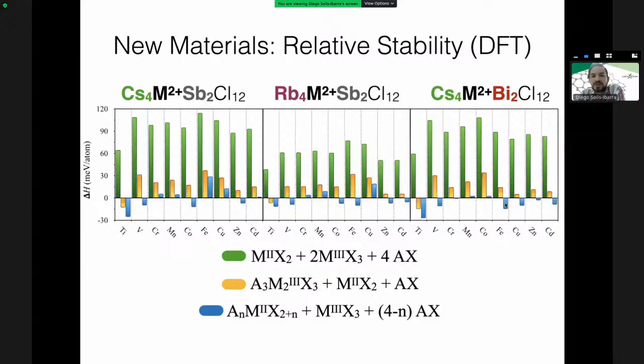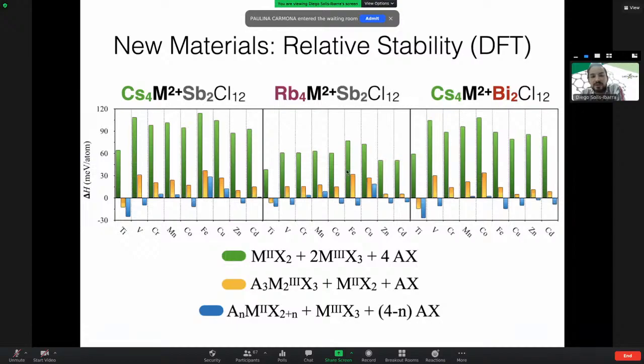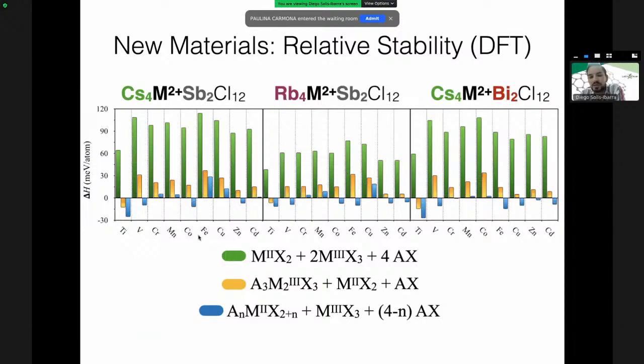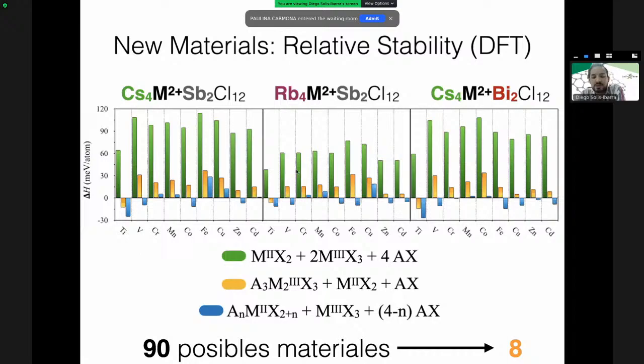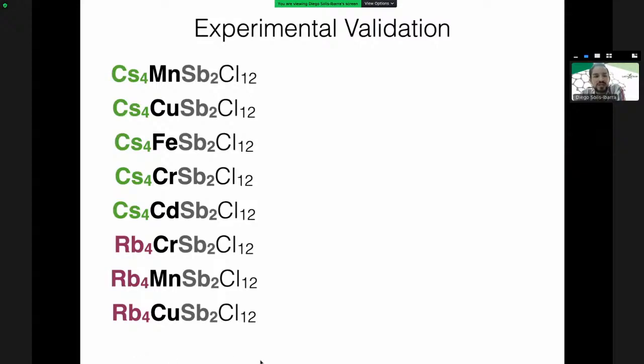Then she used DFT to calculate the relative stability of the materials as compared with the possible degradation compounds. And what ended up happening after all this is that out of 90 possible materials, we end up with 8 that our calculations and our estimation suggested are stable. So 8 is a more decent number, and it's a number that we can experimentally try.